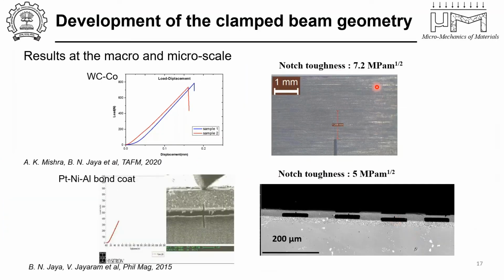This again we tested for a material with a not so well established fracture toughness, which is the tungsten carbide cobalt in the bulk, and we obtained for a high strength tungsten carbide cobalt a value of about 7.2 MPa root meter. So the behavior was linear elastic up to the point of failure. But as you can see, the crack even in tungsten carbide cobalt has grown to a certain extent and stabilized because it's a clamped beam geometry. If this was 3-point bending, then it would have gone through completely.